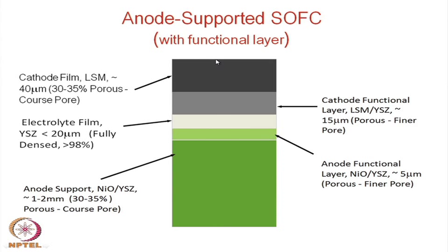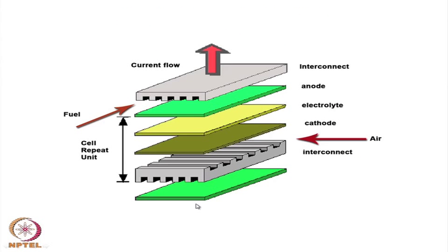The same thing happens in both the cathode as well as the anode side. So, that is the reason one uses a 5-layer model instead of a 3-layer model. One can use a 5-layer model with a gradient of porosity, and sometimes these materials are different. Here of course, just a mixture of the normal cathode and the electrolyte, or a normal anode and the electrolyte, has been used, but some different materials can also be used to enhance the electrode kinetics. So, this is another way of designing.